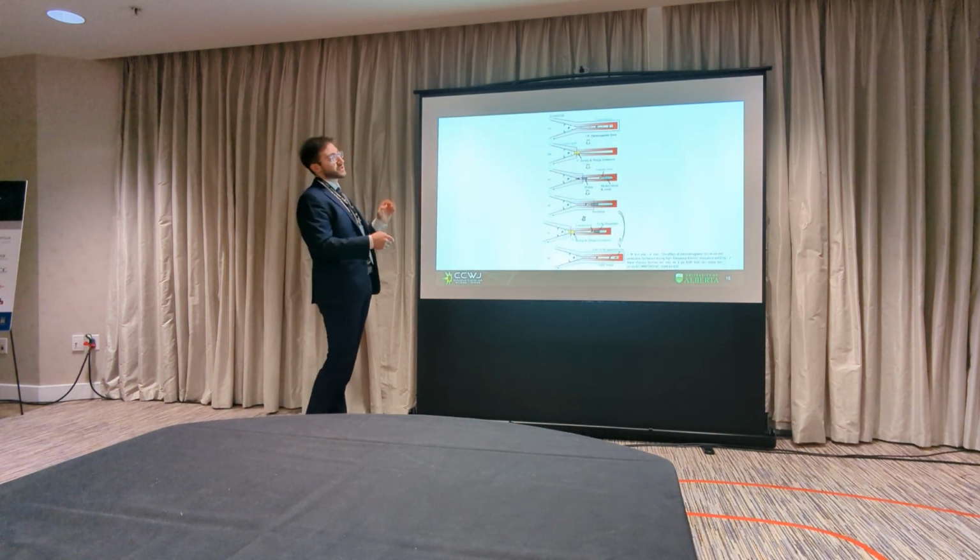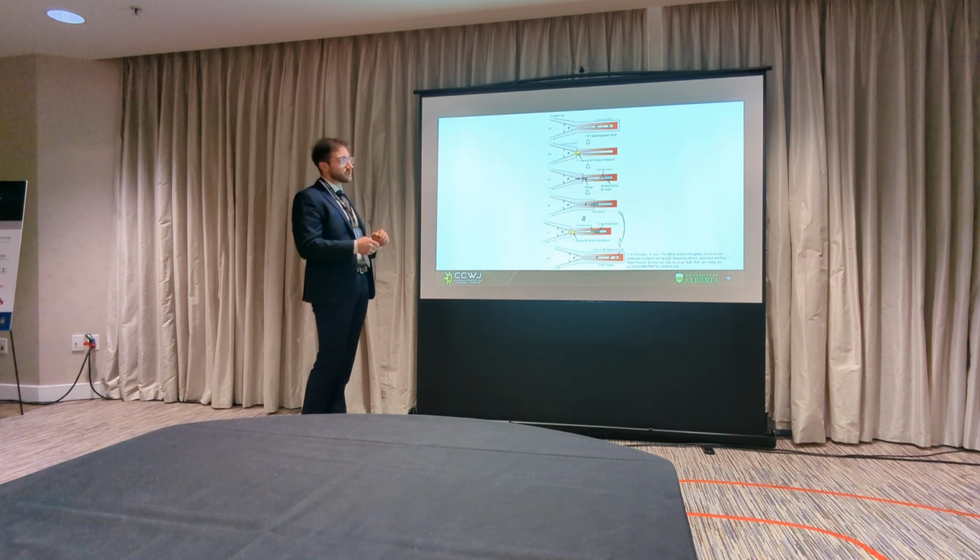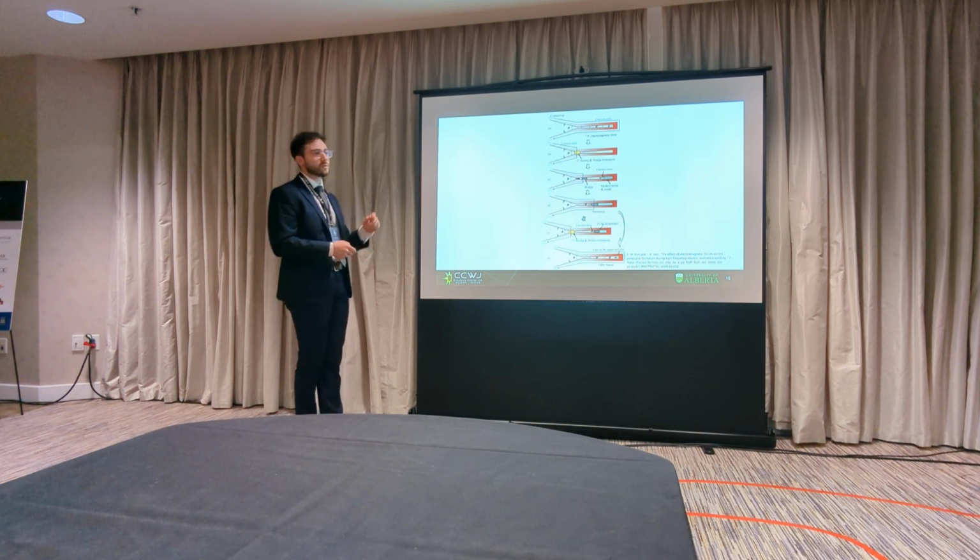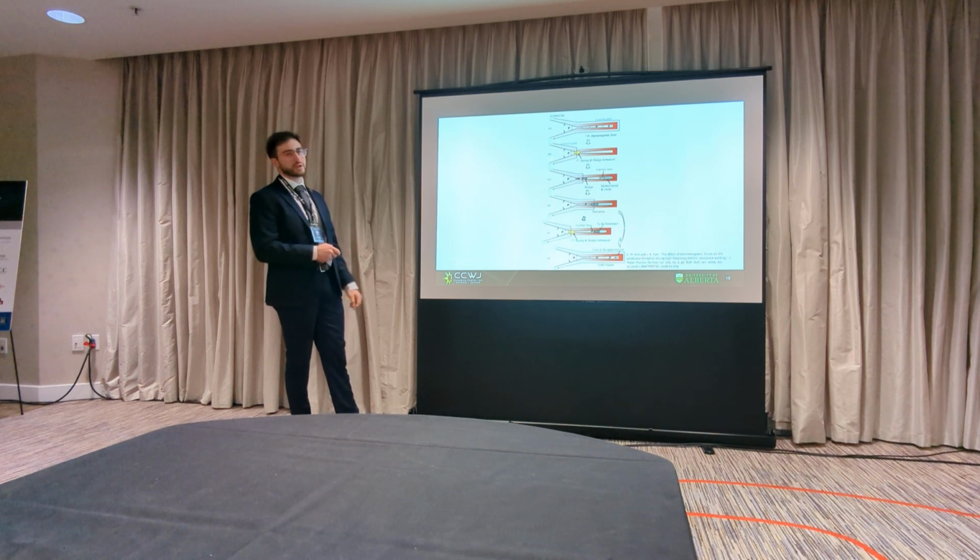So, the first stage, we have your current path, say it's going this way, around the V. We have electromagnetic pressure generated inside the V, okay? When an arc flash event occurs, you get a molten metal bridge, and then now you have an electrical short circuiting through here. So now, after the short circuit, you still have your electromagnetic pressure behind the V, but you have nothing downstream.